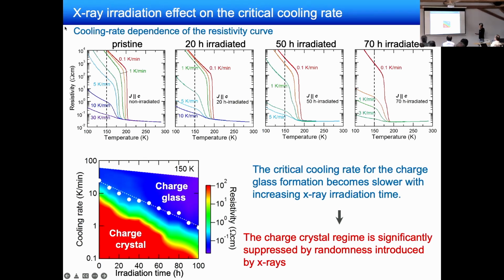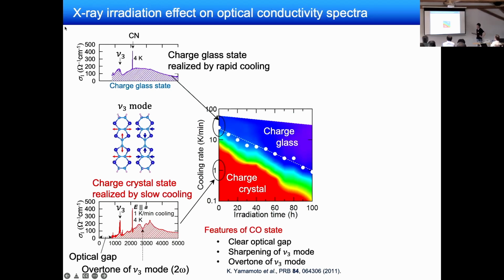Next I will show the result of the optical conductivity data. We measured optical conductivity at each point in this figure. For the present sample, as already discussed, there is a large difference between the charge glass state and charge crystal states. In the charge glass states, the optical conductivity spectra show a very broad peak, while in the charge crystal states, there are several characteristic features, such as a clear optical gap, this very sharp nu3 peak, and also a deep structure coming from the overtone of the nu3 mode.